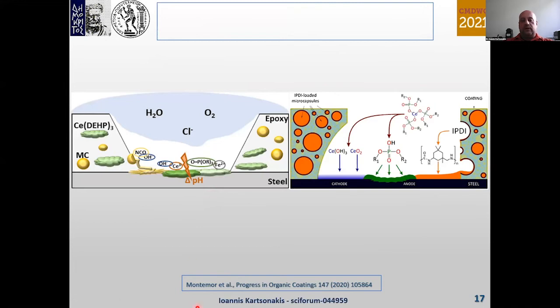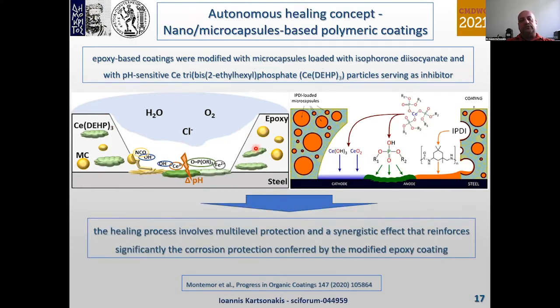In the work of Montemor in 2020, epoxy-based coatings were modified with microcapsules loaded with isophorone diisocyanate and pH-sensitive cerium(III) bis(2-ethylhexyl) phosphate. These particles were used as inhibitors. We can see that after the crack formation on the coatings, there is a variation of the pH and there is a release of these particles and compounds from the microcapsules. So the healing process involves multi-level protection as well as a synergistic effect that significantly reinforces the corrosion protection that the modified epoxy coating can perform.